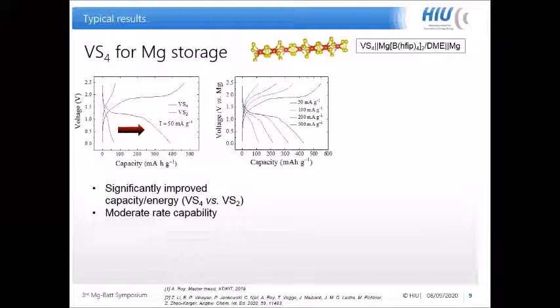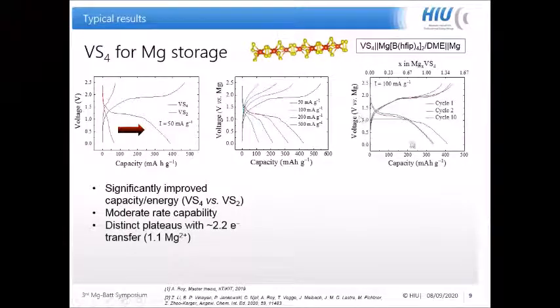Yes, this is actually a good question. As we have presented in the publication, but I didn't show you here, we always have a relatively low Coulombic efficiency, or we have more charge than discharge. Theoretically we could achieve 1.5 magnesium insertion, and in the real case, this only corresponds to around 1 magnesium insertion. So I'm also wondering whether we make full use of the cathode materials here.